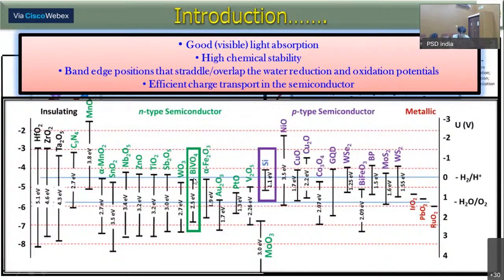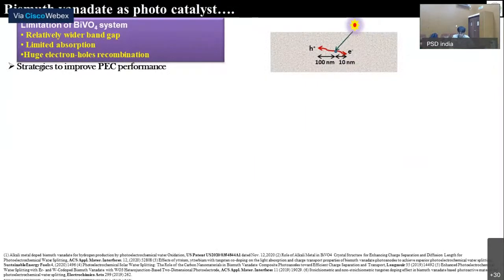So if we take pristine bismuth vanadate as a system and do the water splitting, it shows very poor behavior. There are two reasons for that. One is it has a little wider band gap, 2.5 electron volt. That limits its absorption, which we can overcome by increasing the thickness of our photocatalyst film. But there comes the second part, that it has huge electron hole recombination.